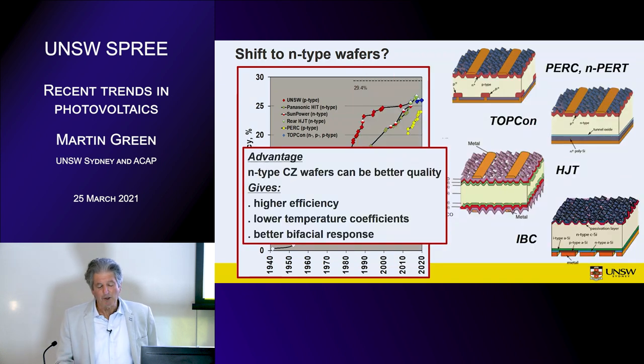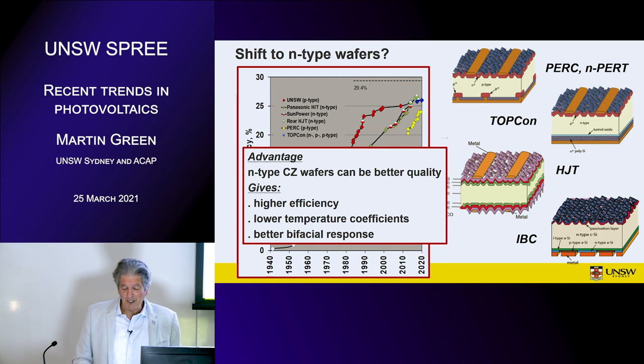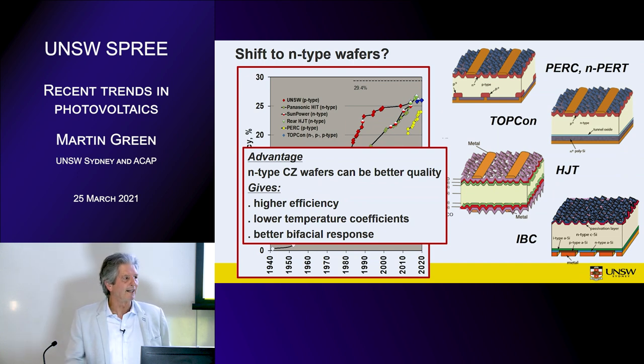You need really good quality. And then for the IBC, you need very good quality for a different reason. Most of the carriers are actually generated within the first micron or so of the top surface, so they have to find their way over to the back. If you just had a planar collector along the back, if your diffusion length was any less than 10 times the wafer thickness, you'd lose 1% of your carriers.